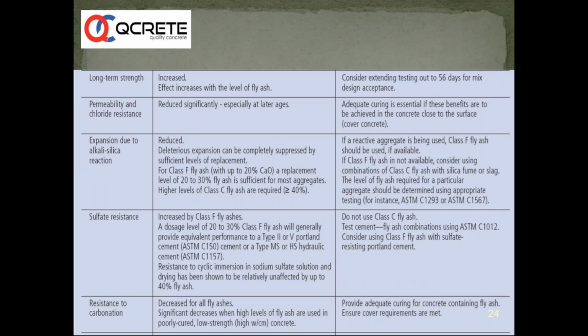Long-term strength is increased. In many other countries, they have started specifying 56 days and 90 days strengths actually. Permeability is reduced significantly, especially at later ages. So the RCPT value, which is a very, very important quality parameter, especially in coastal areas and marine structures, improves at later ages, and hence it has a significant effect and benefit.